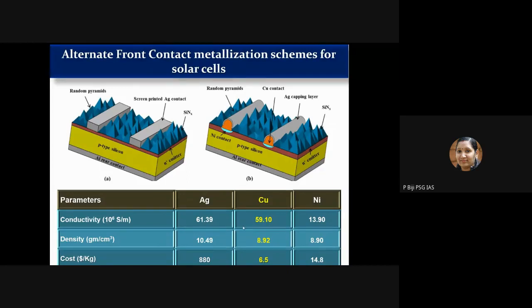So that's the advantage. There's a very good future we can see for copper if you use it as a nickel copper contact. If you see the cost, there is a huge variation. You already know that silver and gold prices are increasing like anything, and at some point we don't know where this will end up. If you compare copper and silver cost, there is a huge variation, almost 880 to $6.5 per kg. So that's the difference in cost, and nickel also is not very costly. So this can be considered a good alternative metallization for solar cells.